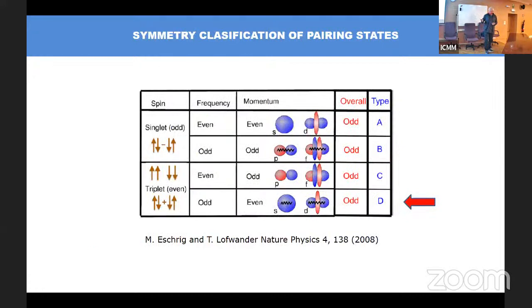But in addition, these triplets have interesting implications in the symmetry of the pairing, right? Because the wave function has to be an odd function under the exchange of the electron coordinates according to the Pauli exclusion principle, right? So if you need the proximity effect to be long range, the pairing has to be isotropic. And isotropic means, in principle, S wave. It could be different, but in principle, say S wave, right?